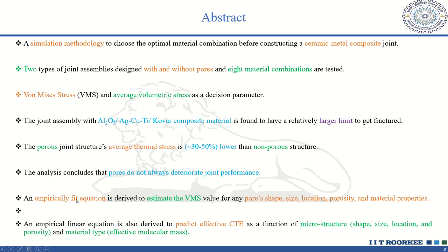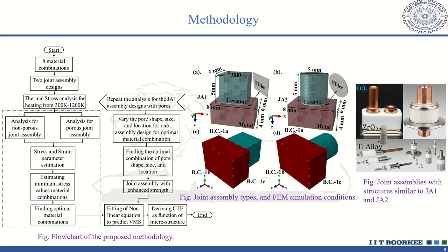An empirical fit equation is derived to estimate VMS value for any combination of pore shape, size, location, porosity, and material properties. An empirical linear equation is also derived to predict the effective CTE of the joint as a function of microstructure and material properties.